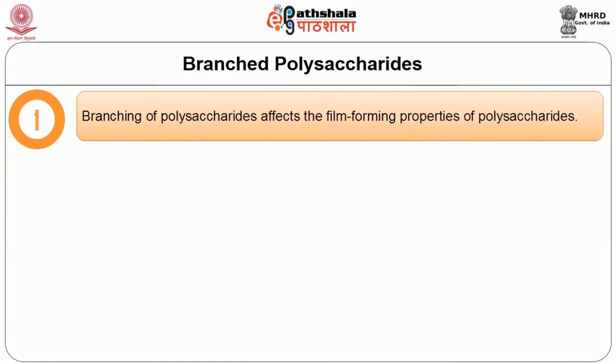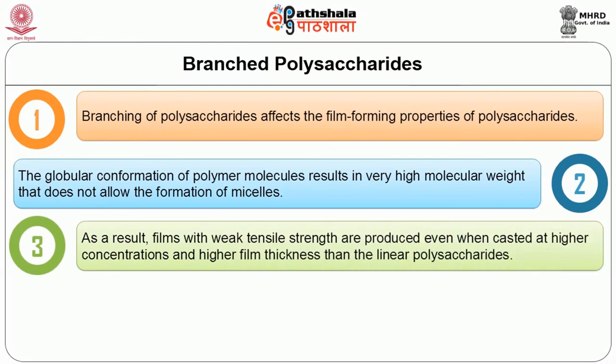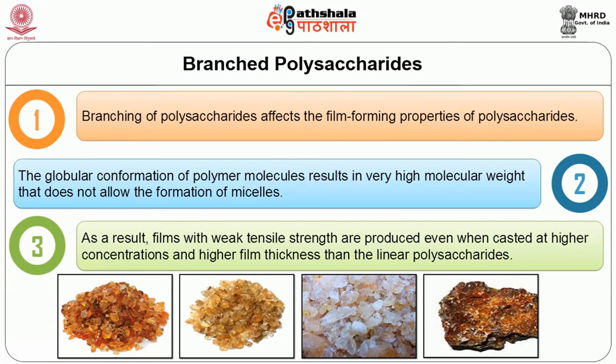Branching of polysaccharides affects the film forming properties of polysaccharides. The globular conformation of polymer molecules results in very high molecular weight that does not allow the formation of micelles. As a result, films with weak tensile strength are produced even when cast at higher concentration and higher film thickness than the linear polysaccharide. Examples of such include gum arabic, ghatti, karaya and larch gum. These, when applied to form a film, do not peel off in one piece, instead have the tendency of flaking